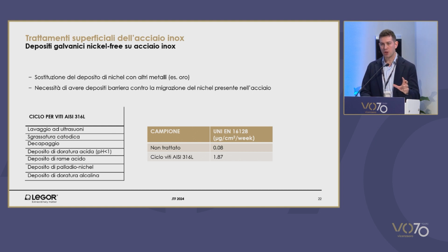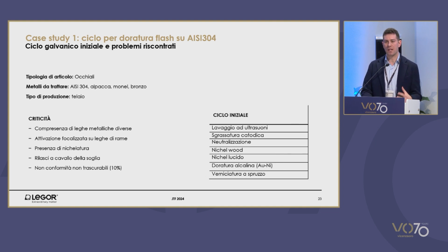This is a project that we've carried out at LEGOR, where electrodeposition was performed on screws to be used in eyewear using 316L stainless steel. The release is not compatible with the rules. The same screw that was subjected to electrodeposition was releasing nickel 5 times more than included in the regulation. So the barrier was not sufficient.